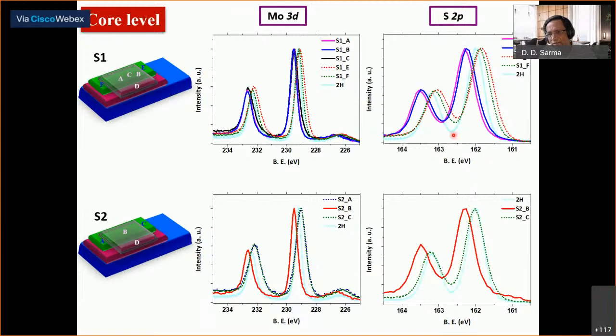There's a sky blue line, which you can hardly see, from the reference 2H structure, which tells me that all of them have exactly the same line shape. It's actually H phase everywhere. There's no trace of T phase in any of this. So the speculation that the compressive stress drives MoS2 into the T phase, one of the T phases, is wrong. But there is a large shift that you can see, 0.4 electron volt.